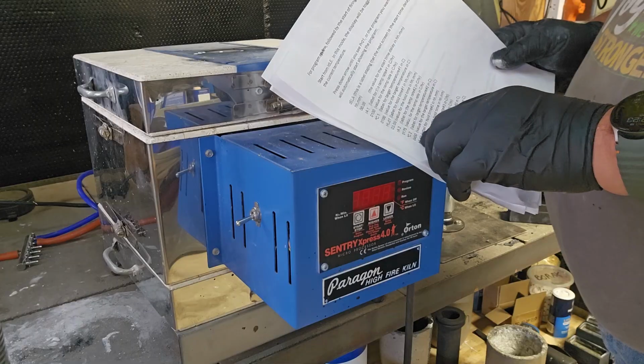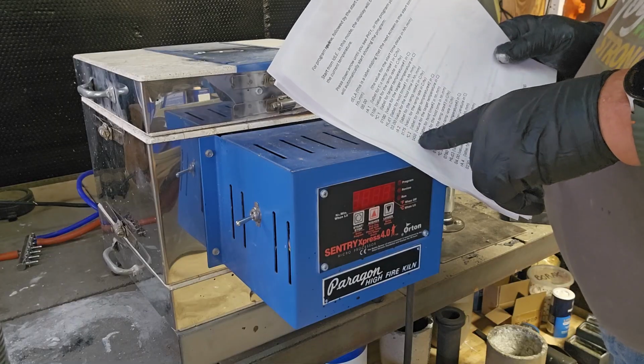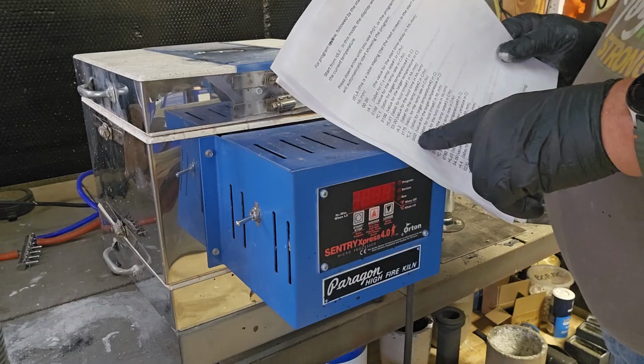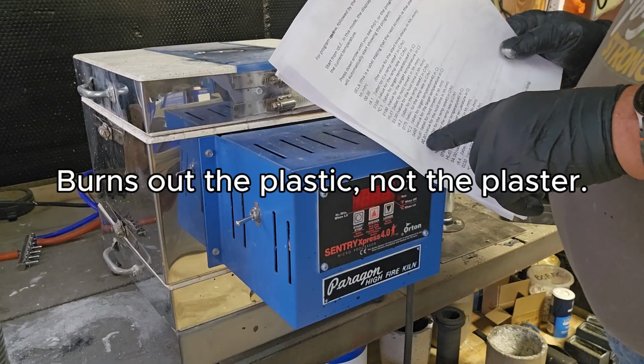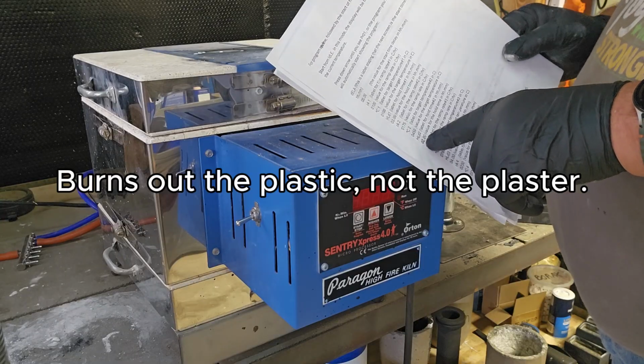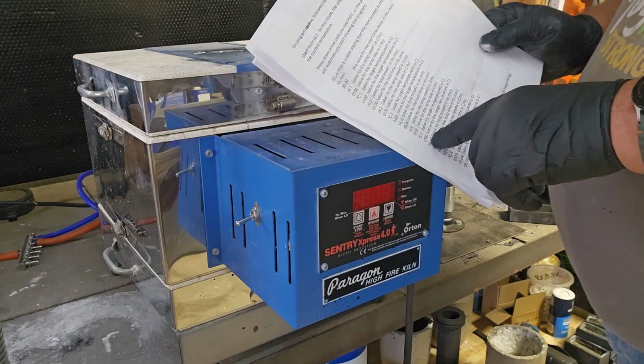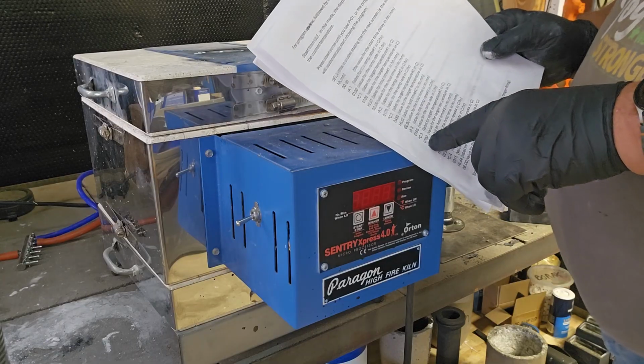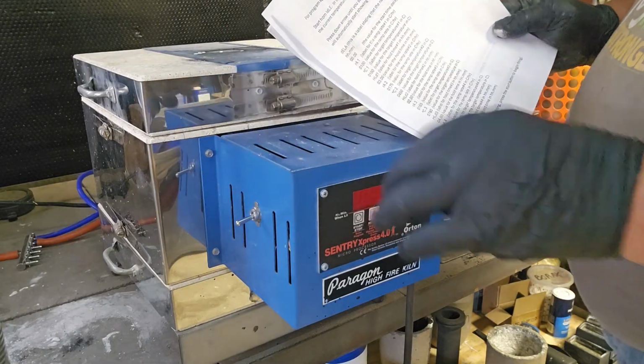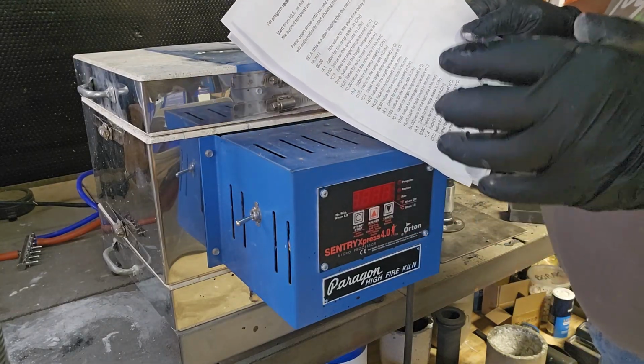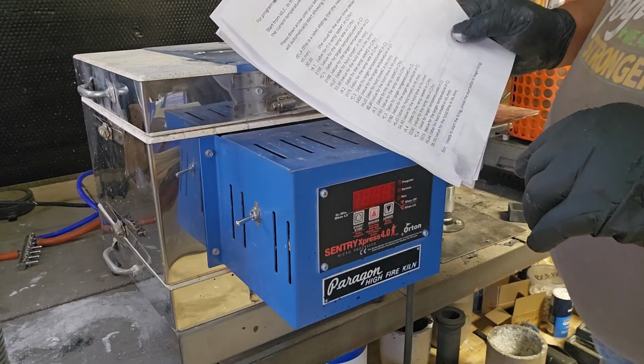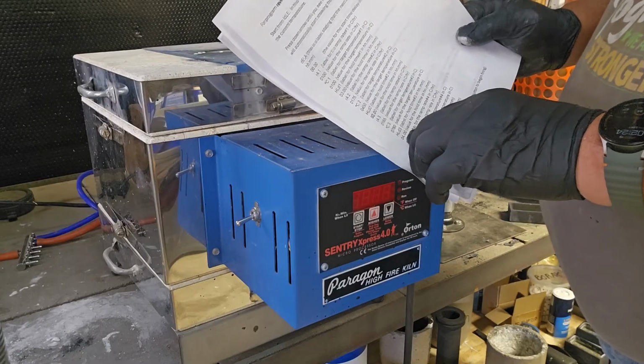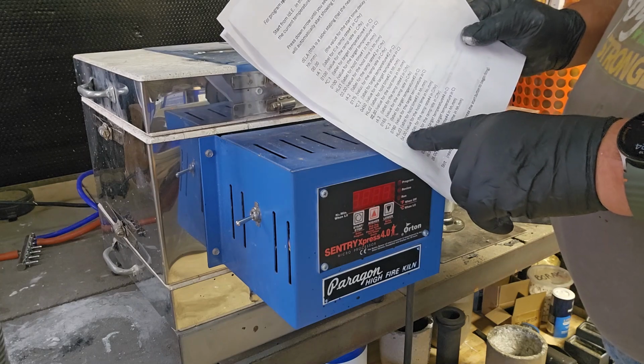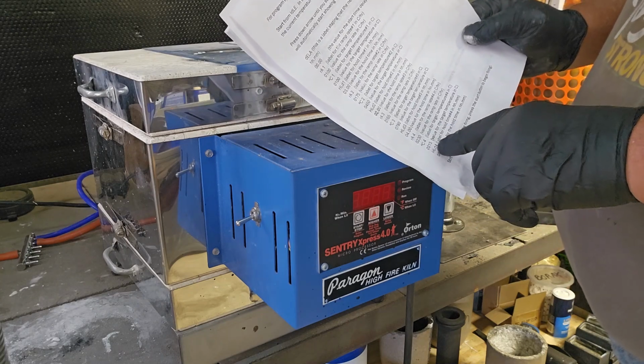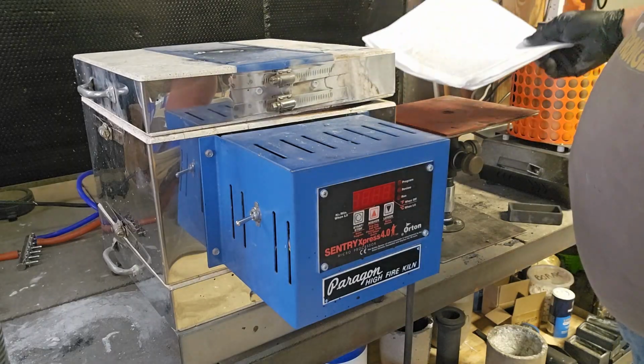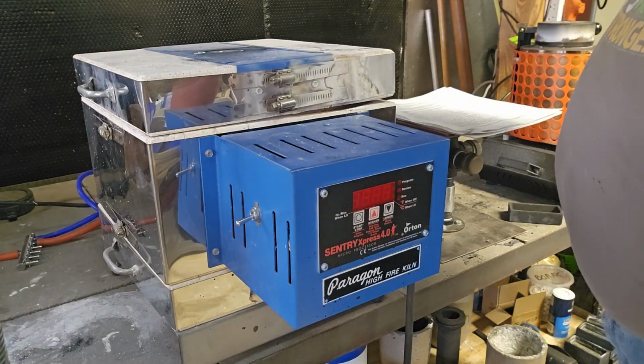Then you ramp it up to 450 C, which burns and melts out all the plastic. You hold it at 450 C for 2 hours. When that's done, you ramp it up to 780 C, which kind of sinters the plaster and the other stuff in there so it sticks together and it's more rigid and more sturdy. You hold it at that 780 for 4 hours, and then you cool it down to whatever temperature you want to preheat the mold at.